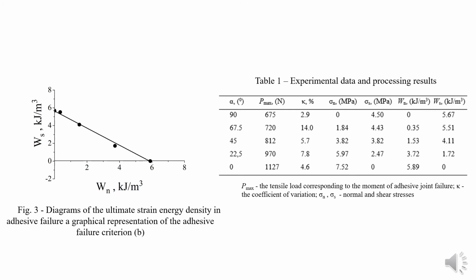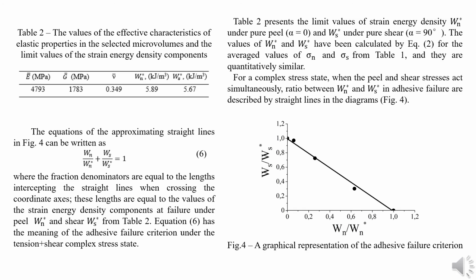Table 1 shows the values of sigma n, sigma s, Wn, and Ws calculated for the averaged values of Pmax. Figure 3 shows graphical interpretations of the data from Table 1. Table 2 presents the limit values of strain energy density Wn asterisk under pure peel, alpha equals 0 degrees, and Ws asterisk under pure shear, alpha equals 90 degrees. The values of Wn asterisk and Ws asterisk have been calculated by Formula 2 for the average values of sigma n and sigma s from Table 1, and they are quantitatively similar.